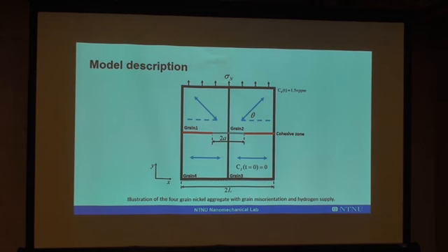For hydrogen embrittlement simulation, we supply hydrogen to the outer boundary of this aggregate, and we leave the interior hydrogen free. Upon loading, we allow hydrogen to diffuse, driven by the hydrostatic stress field, and redistribute to the local sites. For hydrogen diffusion, we consider 2 subcases. The first one is the steady state diffusion case. The second one is the transient case, which will be elaborated later. For all the cases, we apply uniform tension at the top, and in the loading process, we update the cohesive strength, that's sigma C, from time to time, according to the hydrogen concentration.